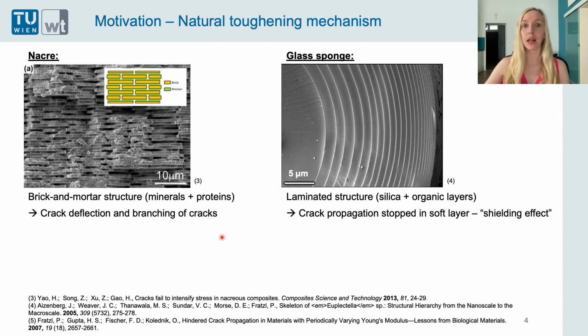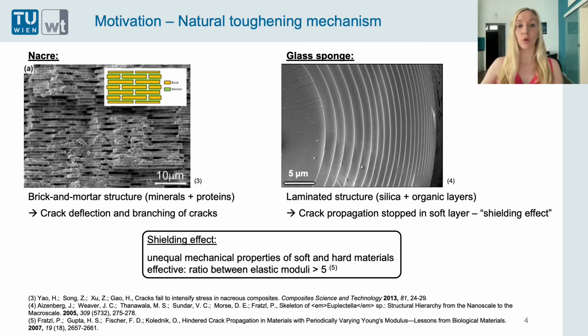And another example are glass sponges. Here you have laminated structures with alternating silica and organic layers, and the crack propagation is stopped in the soft layer due to the shielding effect. So what is the shielding effect? It happens due to unequal mechanical properties of the soft and the hard material, and it's effective if the ratio between the elastic moduli of the two materials is at least 5 or higher. And we want to use this shielding effect to toughen our materials.